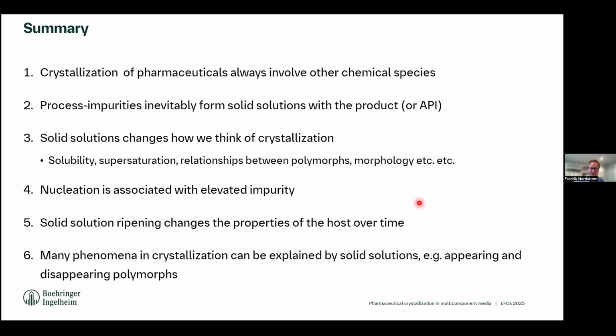And the other thing is we see that nucleation is associated with a much higher impurity load, and that we have this solid solution ripening that takes place over time. And if you compare these solid solution formations with many other phenomena in crystallization, you can give a lot of explanations to how they actually happen, like appearing and disappearing polymorphs, twinned crystal growth, and so on.